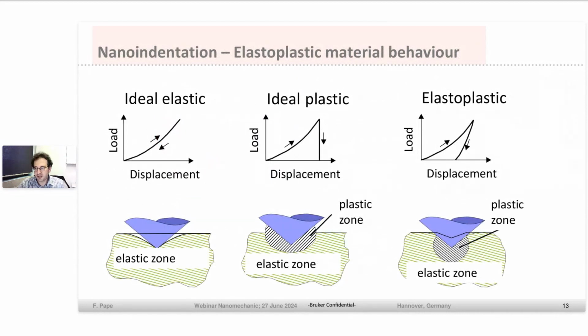So the material response is shown here. It can be more elastic on the left or ideal plastic. In this case, there's just the indent and no elastic response of the material. And typically for our steel substrates and also for the tribofilm, we have this elastoplastic response. That means there's a plastic zone below the indent, but also some elastic properties of the material.